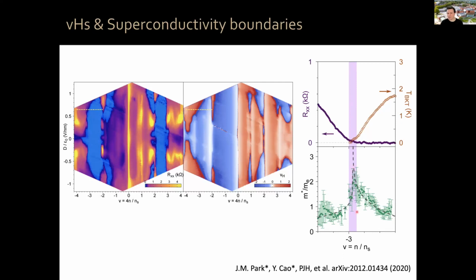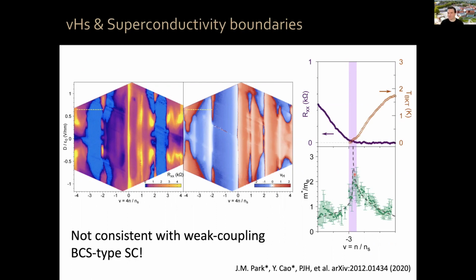So we can see that not only does it look like a van Hove singularity because of this feature in the Hall density, but it also has a diverging effective mass, as you would have, density of states is diverging at that point, okay? And what you can see is that Tc, rather than increasing as your density of states gets higher and higher, actually decreases.